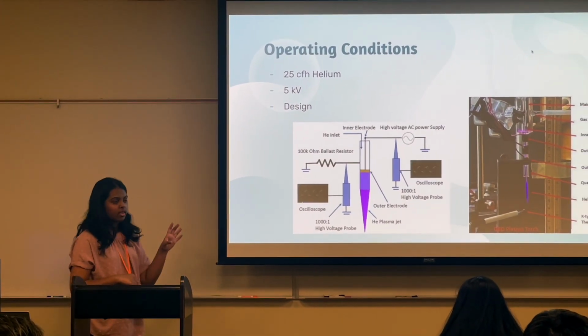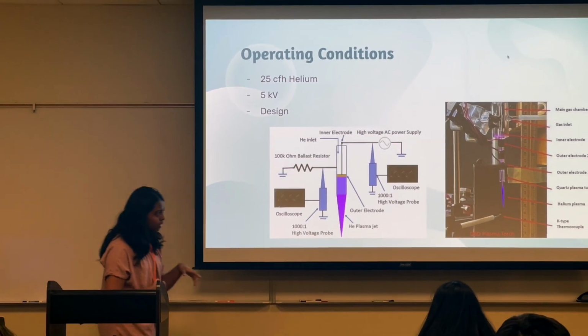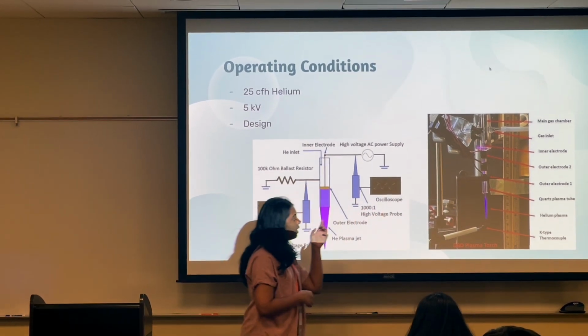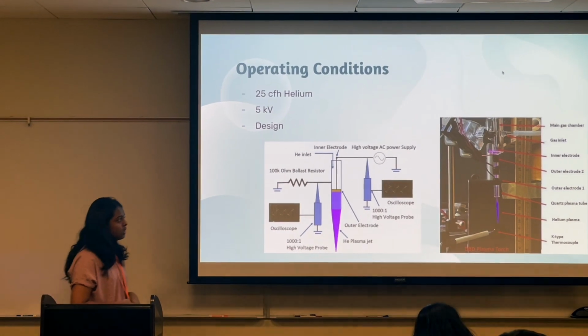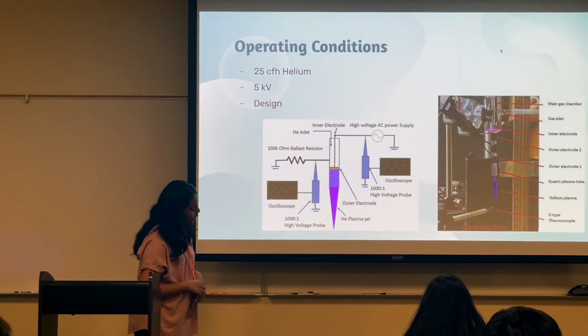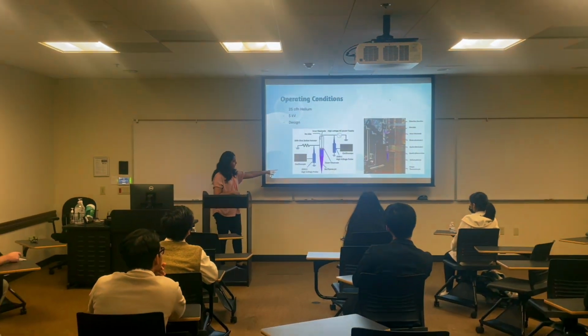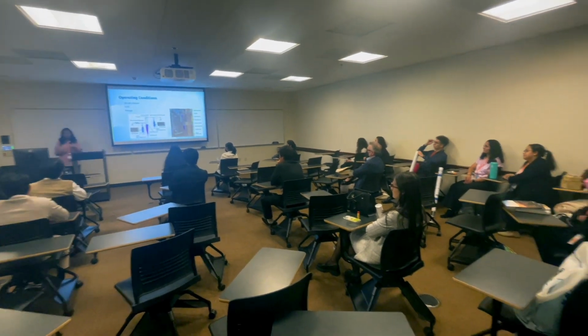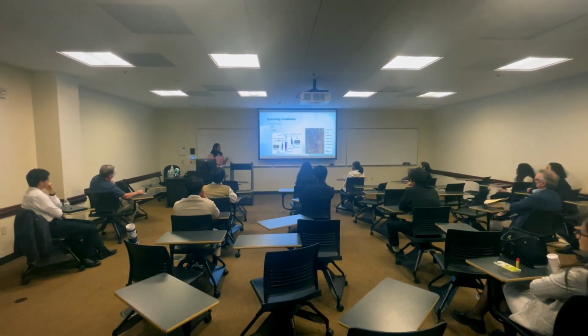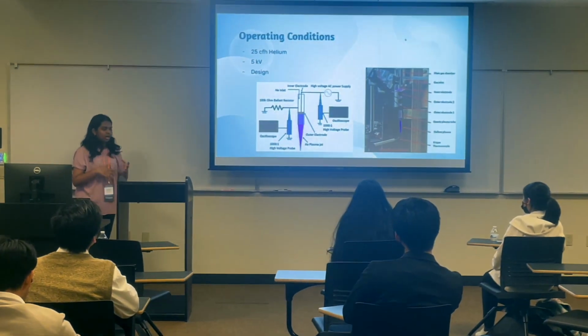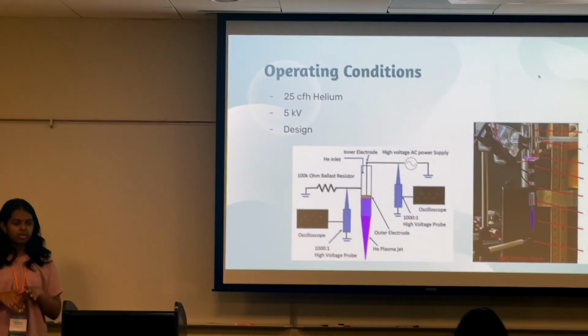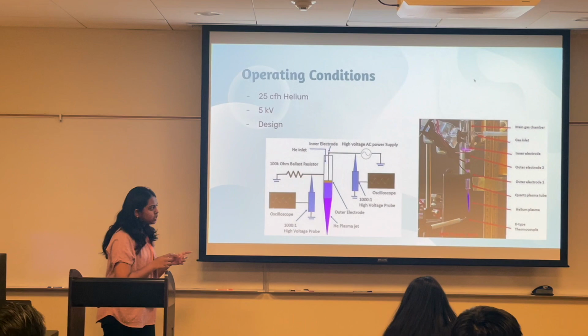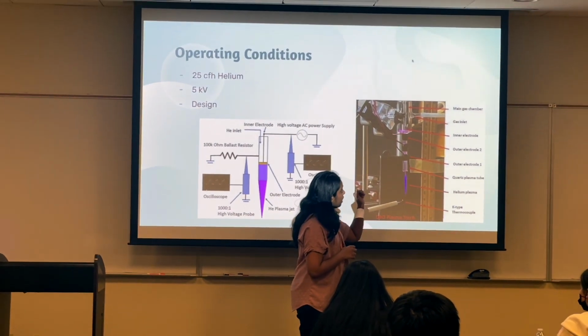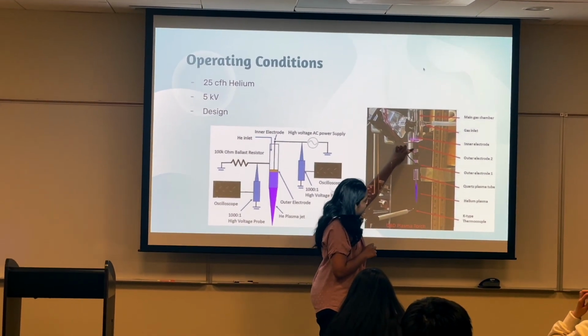So over here, this is kind of like a design of how our torch works. Over here we have a DBD plasma torch, which is generating the plasma jet from the torch, and it's currently connected to the lower electrode, it looks like. And over here we have the circuit that allows electricity to go into the plasma torch. So we input a 5 kilovolt voltage, at around 30 kilohertz of frequency, into the plasma torch, and we pass that through a 1000 to 1 high voltage probe to reduce the amount of voltage that goes directly into the plasma jet. And because our plasma jet is basically two electrodes over here separated by a dielectric material, which is like that tiny rod up there, if you can see that.